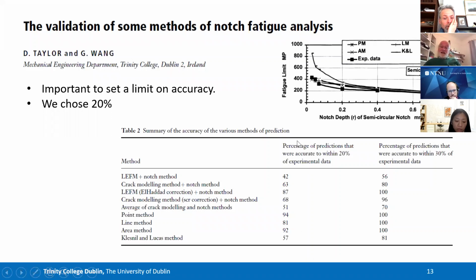So here is the percentage of all those individual data points from all the papers we looked at that were accurate to within 20% on stress or 30% on stress. And I think that's an important point as well, that we wanted to set for ourselves a limit on accuracy that described whether we were being successful or not. And we chose 20%. The reason we chose that was we said, look, there are errors here that we can't avoid. There's an error in these fatigue limit results. There's always some scatter in fatigue, and that's probably at least 10%, right?